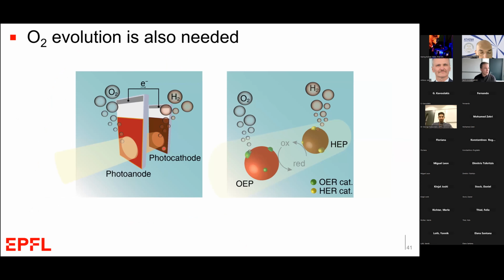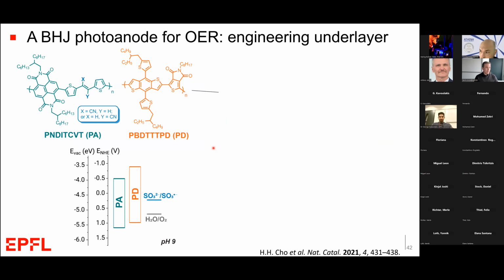And the last part of the story then, as we've shown, we can make hydrogen with these organic semiconductors. Can we also make oxygen with a photoanode with these organic semiconductors? This proved to be quite difficult. Not only do we have to find organic semiconductors that have the right energy levels to oxidize water, but also can be reasonably stable under the harsh conditions. We haven't done great at that, but we have identified a system based on these two polymers here as the acceptor and the donor, which do have the appropriate energy levels for water oxidation.